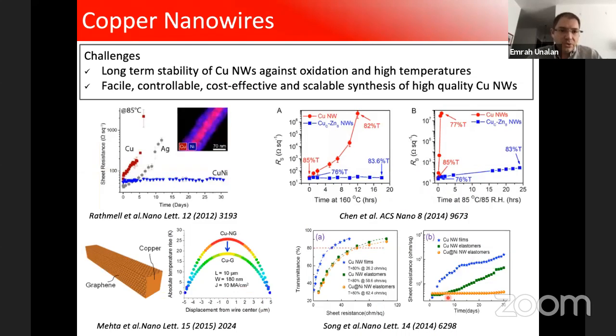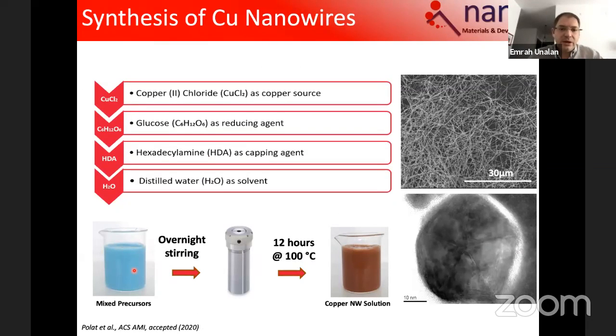And then let me switch gears now, talk about the copper nanowires, because as I said earlier on, copper is a very cheap alternative compared to silver nanowires. But the problems are bigger these days with copper. So the long-term stability is a problem, and the facile, controllable, cost-effective and scalable synthesis of high-quality copper nanowires was an issue. And I believe we also solved that to some extent. So for the stability, if you look into literature, what has been done is to put nickel on top, or zinc on top, or tin on top, or coating it with graphene or graphene derivatives like reduced graphene oxide. They were the solutions in literature. And I will explain our solutions to that.